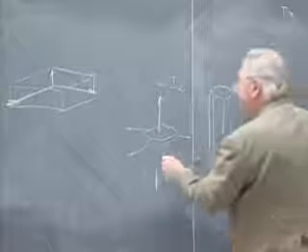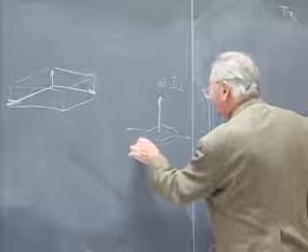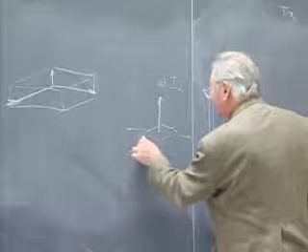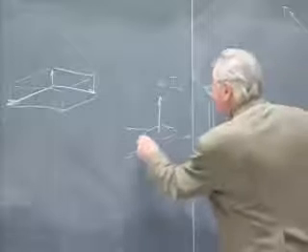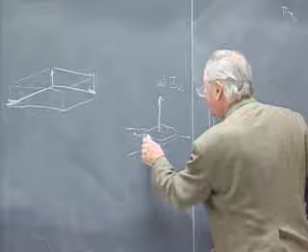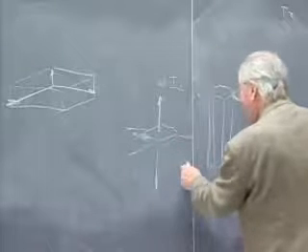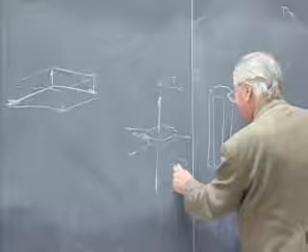The interpretation was that in the early stages of growth, the crystal is growing by accretion of atoms onto these planar surfaces. And the probability of an atom sticking is less high when the atom is on a flat surface than when an atom is on a surface that might have a little crevice in it so it can bind to two planes at once.